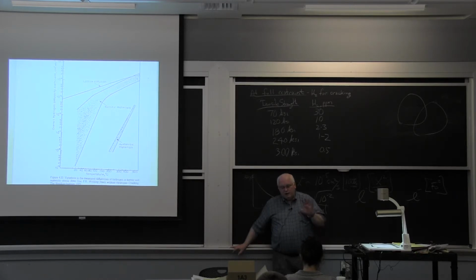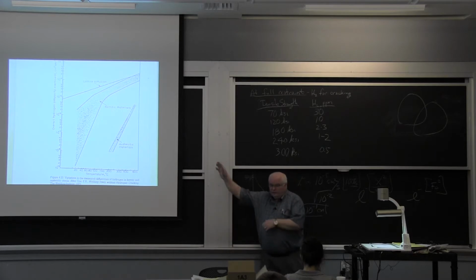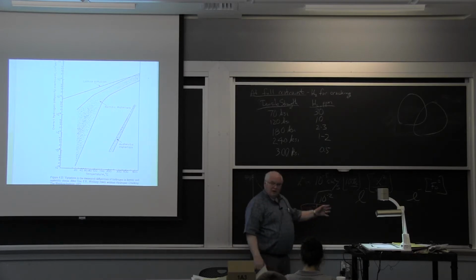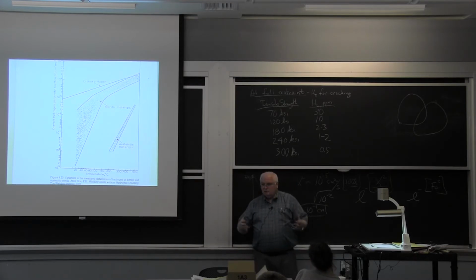The spec from ASTM says that you must put it in the furnace within 1 to 4 hours for electroplating to get rid of the hydrogen. Why? Well, I just went through the calculation here, roughly. If you don't get it in there within an hour, it's liable to migrate and diffuse to those crack tips, a millimeter or whatever, to whatever the imperfection is, and the thing could crack.